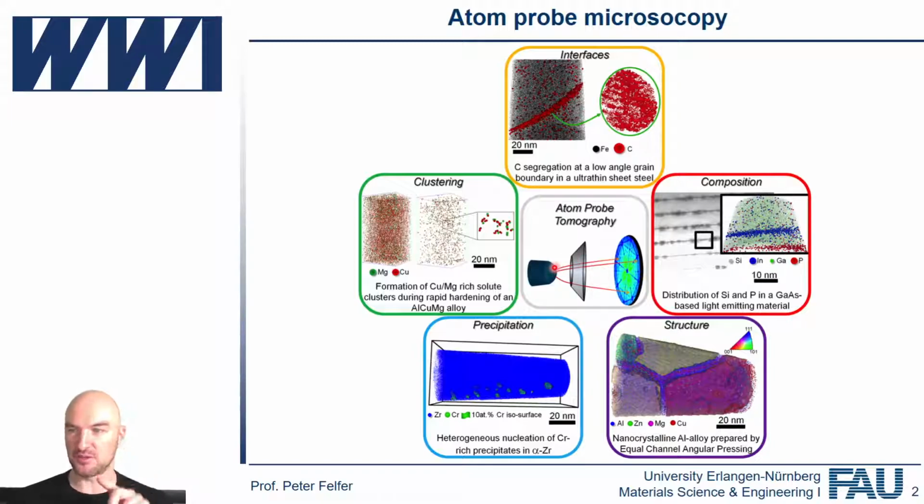And if you're some tens of nanometers or some hundreds of nanometers away from the sample, that's actually a fairly homogeneous electric field. And so the image that you get is actually fairly reproducible. If you're very, very close to the sample, the field is not as homogeneous, but that's a topic for later today. Okay, but we essentially get a transfer of whatever local electrostatic field we have on the sample onto some macroscopic screen.